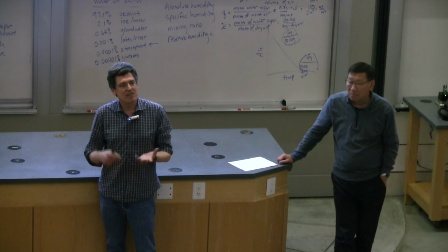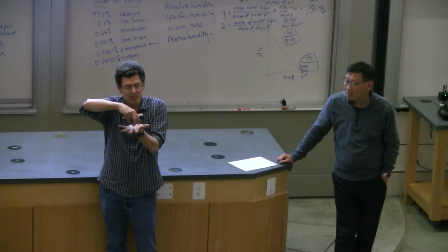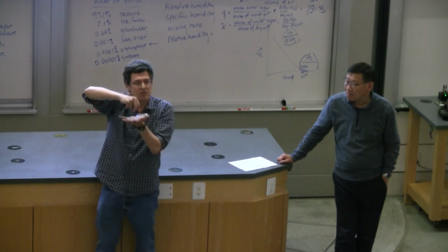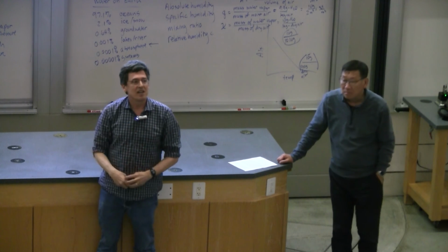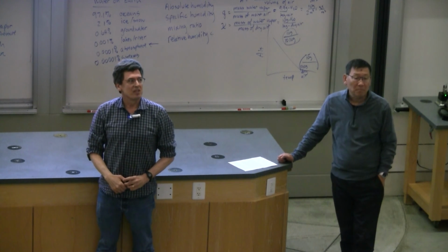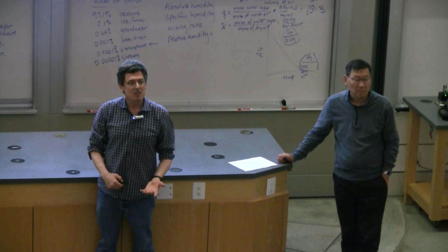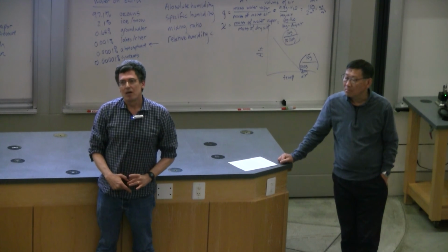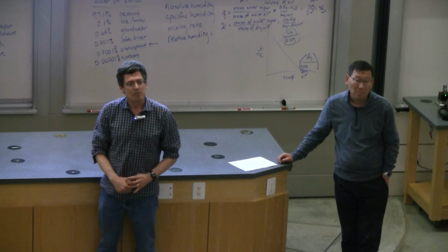I think a question that you have to ask is, what's the energy of excitation? How much energy does it take to take one of these electrons out of the Wigner crystal and put it into, for example, an interstitial site? And that energy, we think, is on the order of 25 millielectron volts, and so that's actually pretty high temperature. But that, I think, is the relevant energy scale.